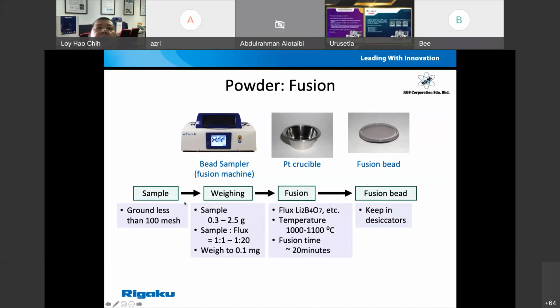This is the example process. We grind the samples as fine as possible and ensure that it's less than 100 micron or even 44 microns. And we weigh the samples. In fusion, we actually use a very small amount of sample, maybe somewhere around 0.3 to about 2.5 gram. But the flux is normally about 1 to 20 or 1 to 10: 1 part of sample, 10 parts of flux.